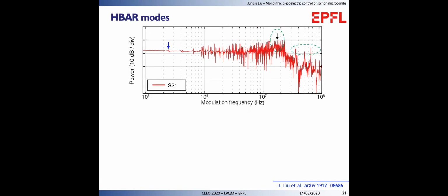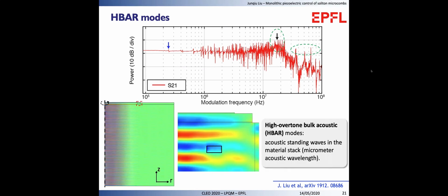The peak around 70 MHz and the multiple of 70 MHz are high overtone bulk acoustic modes, the HBAR modes. HBAR modes are acoustic standing waves in the material stack with micrometer acoustic wavelengths. Our chip thickness is 230 micron, which corresponds to 17 MHz HBAR mode spacing.